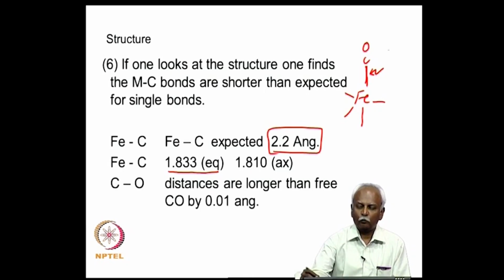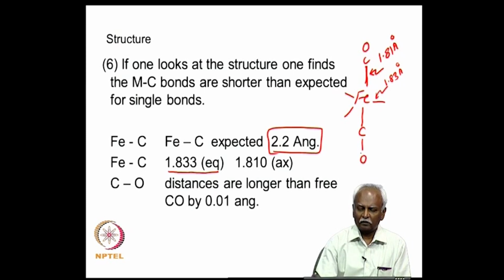The axial bond, surprisingly, is 1.81 angstroms, and the equatorial bond is 1.83 angstroms. So, these distances are shorter than expected. The CO distance is longer than what is observed in free carbon monoxide by 0.01 angstroms. So, you have two things that we need to explain. First of all, the fact that all of them have this 18 electron structure. Secondly, you have to explain the fact that you have shorter bonds than what you expect for a single metal carbon bond. And the third point that we note is that you have a carbon oxygen bond distance which is slightly longer. So, you have a very small elongation of the carbon monoxide bond, and you have a shortening of the iron carbon bond.